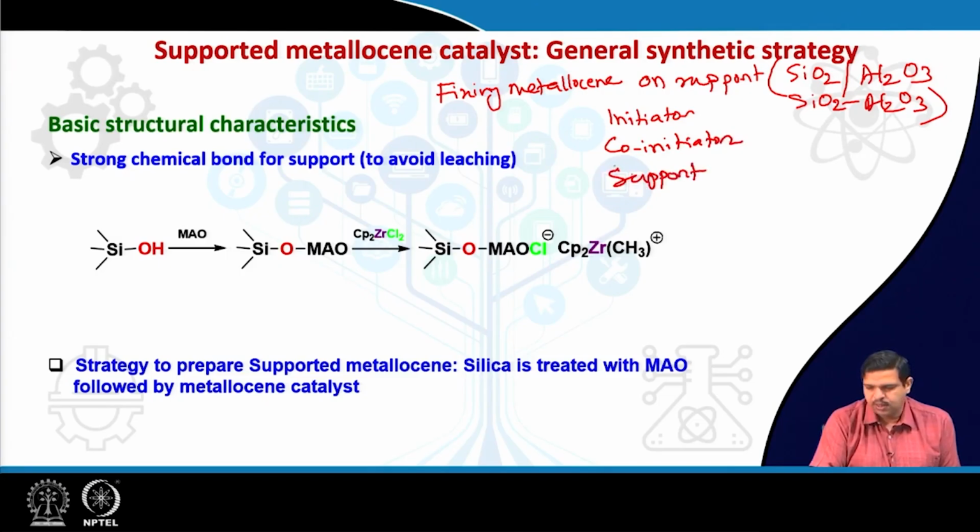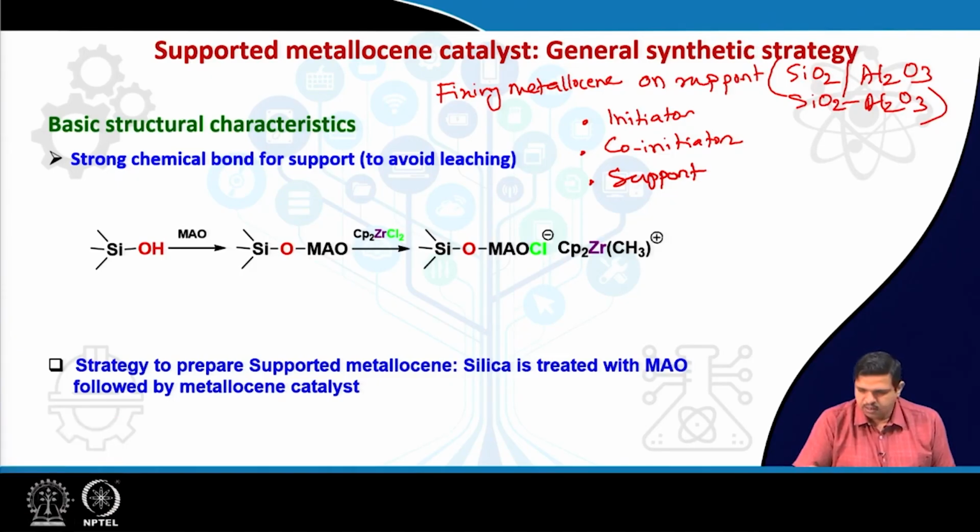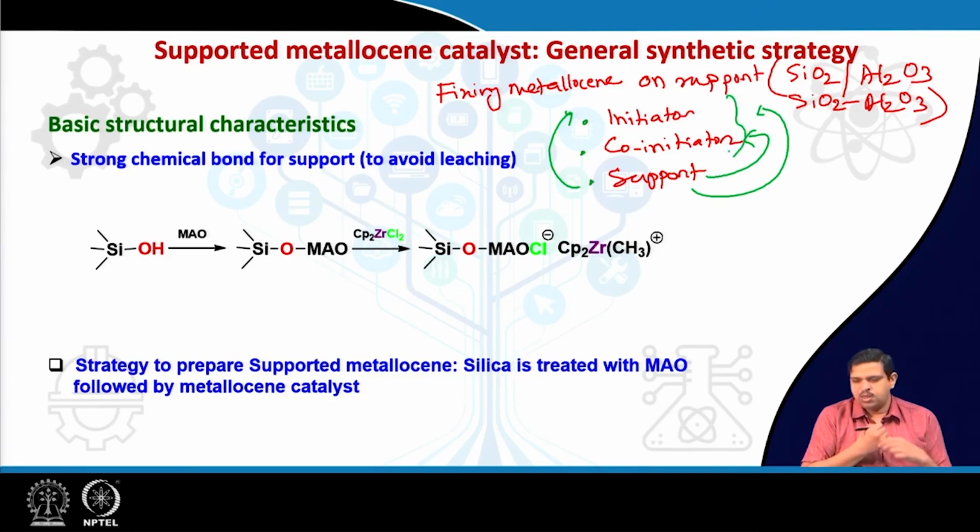Support means silica or aluminosilicates. Either you react the support with the initiator, or the support with the co-initiator, or the support with the initiator and co-initiator mixture. Three ways are possible.